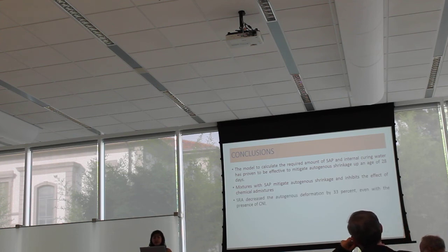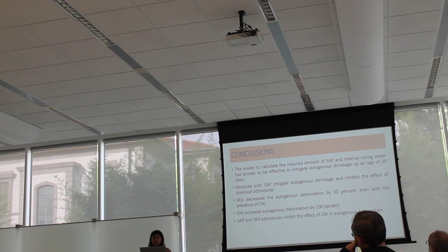Shrinkage reducing admixture decreases the autogenous deformation by 33%, even with the presence of calcium nitrate. So you can use this admixture to mitigate the bad behavior of calcium nitrate on autogenous shrinkage. We conclude that calcium nitrate increases the autogenous deformation by 100%, and SAP and shrinkage reducing admixtures inhibit the effect of calcium nitrate on autogenous deformation.